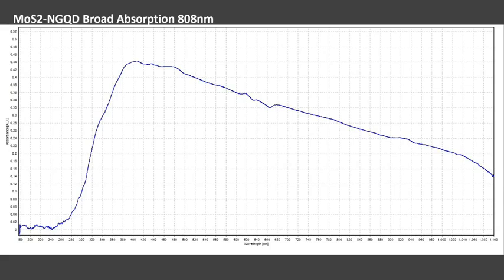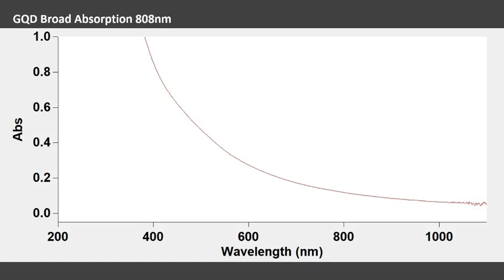And then for molybdenum disulfide, we actually don't see a strong peak at all in the near-infrared region. But this right here is 0. So we're seeing good absorption all the way through that near-infrared region. Even though it's not a peak at where our laser is, we thought there might be enough absorption there to see some denaturing of our cells. And for the GQDs, the reason this graph looks different is it was on a different machine. In the 800 to 1100 region, again, not a strong peak, but there's a broad absorption. So we thought we might give it a try.